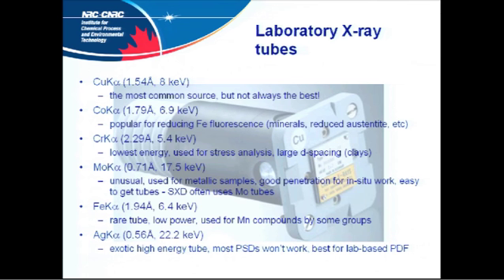Right, this is basically the selection you've got to choose from. Copper is the most common, but not always the best. In many instances, people get a laboratory instrument and automatically that's what they get, so it's worth asking yourself whether that's the right one for the job. Cobalt is probably the second most popular. This is what you'll tend to find in most mineralogy departments. A lot of their materials have iron in, so it's enough of a problem, often enough, that they think about these things. And then you've got some of the slightly weirder ones. Chrome's often used for stress, but as I say, for manganese it does avoid some of the problems.